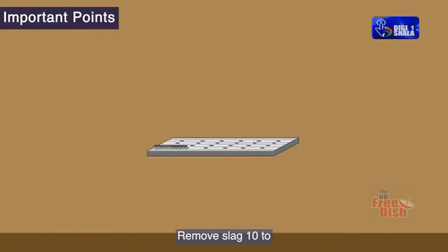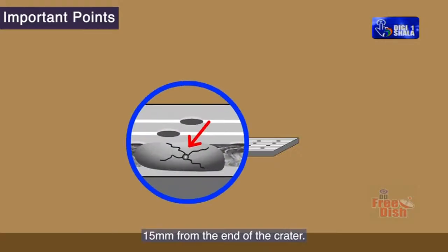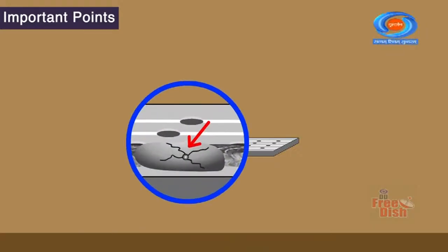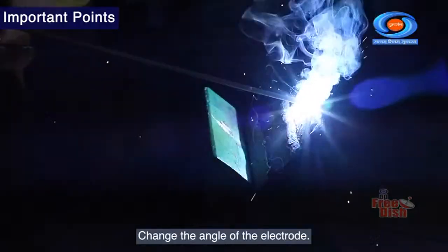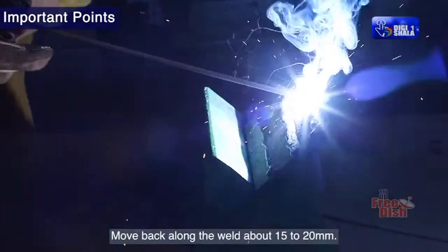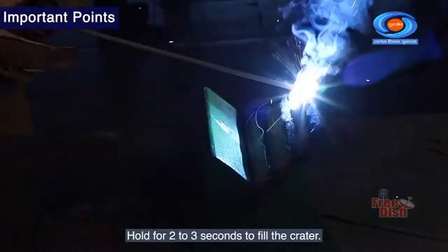Remove slag 10 to 15 mm from the end of the crater. Change the angle of the electrode. Move back along the weld about 15 to 20 mm. Hold for 2 to 3 seconds to fill the crater.